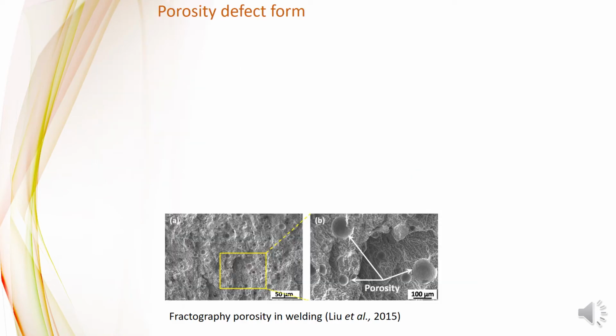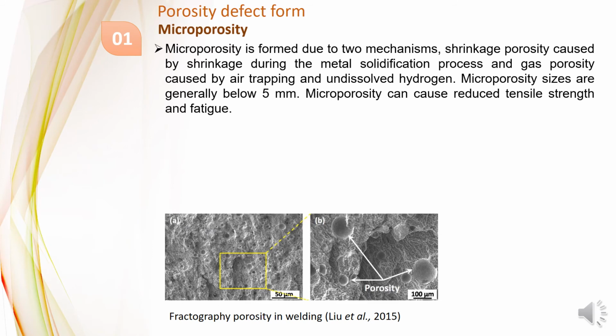Porosity defect form. Number 1. Microporosity. Microporosity is formed due to two mechanisms: shrinkage porosity caused by the shrinkage during the metal solidification process and gas porosity caused by air trapping and undissolved hydrogen. Microporosities are generally below 5 millimeters. Microporosity can cause reduced tensile strength and fatigue.